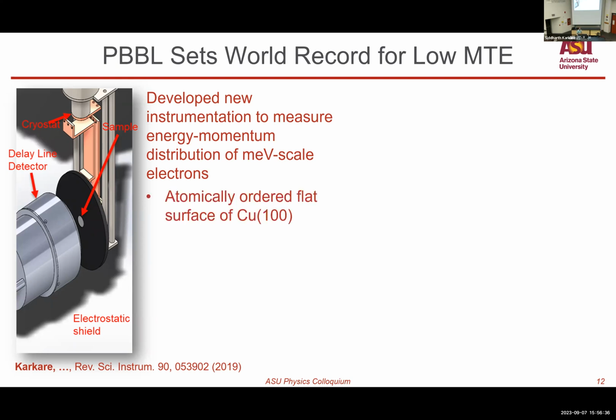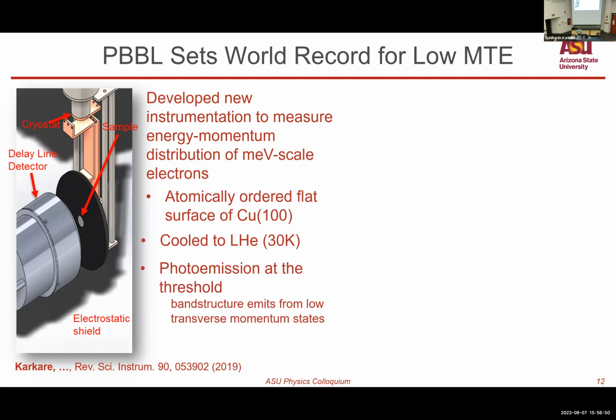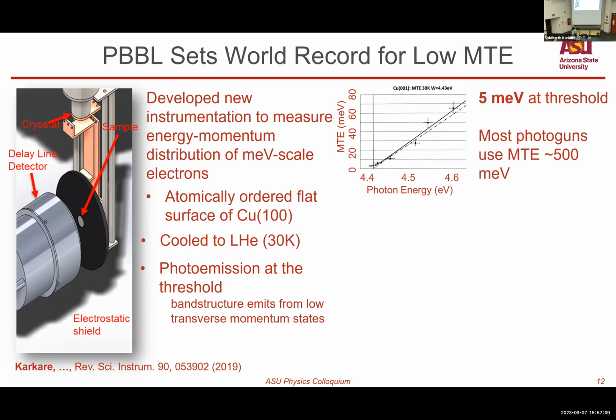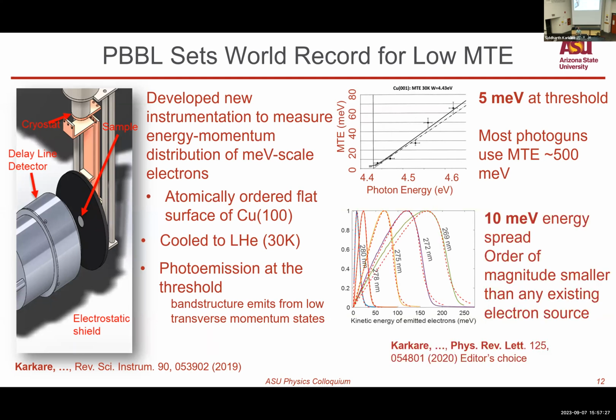We used an atomically ordered surface of copper. We had to prepare it in ultra-high vacuum using several cycles of ion bombarding and annealing to get a really well-ordered surface. We cooled it using liquid helium to 30 Kelvin. And this copper 100 surface does ensure that its band structure is such that electrons are emitted from near the gamma point, so you don't have high transverse momentum states emitting. And that gave us a very, very small mean transverse energy, as small as we were able to measure, 5 milli-electron volts at the photoemission threshold. To remind you again, most photoguns use 500 milli-electron volts. So it's 2 orders of magnitude better than what's typically used. Not just that, we were also able to measure the energy spread.